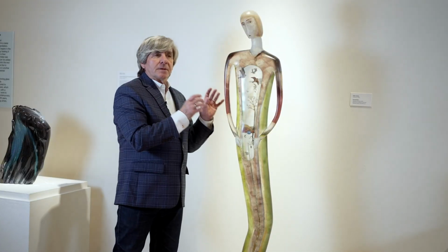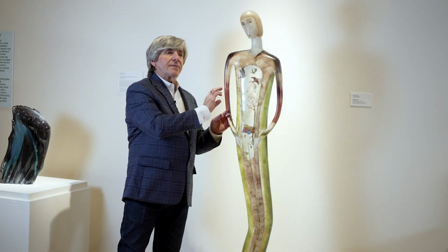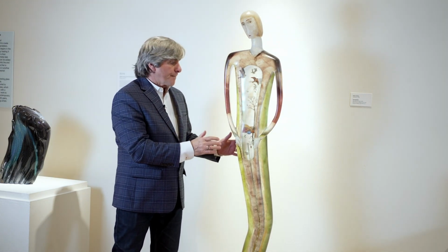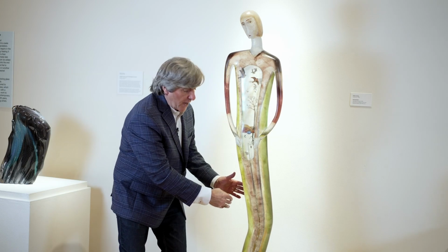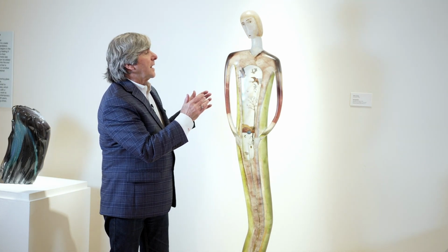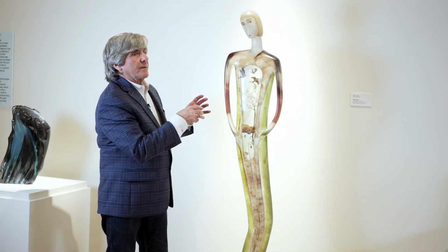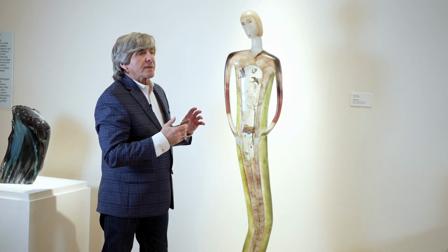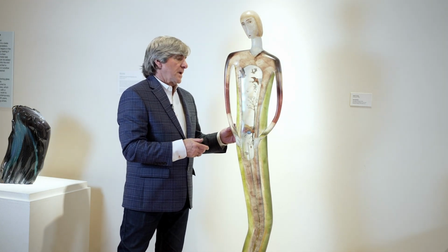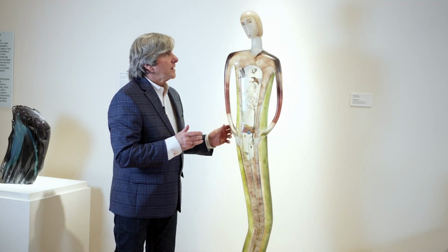So she's got to get the final piece out, and we think, final piece, it's going to look just like this. No, it's still going to be rough. Not very rough, but rough enough that she's going to have to either sandblast or grind or sand in some manner to get the beautiful smoothness that she has. Then apply her color. And then I'm thinking that when she's out of the kiln, the cooling off process for something this size is really going to be upwards of 2 weeks. And you don't want anything to go wrong in that.